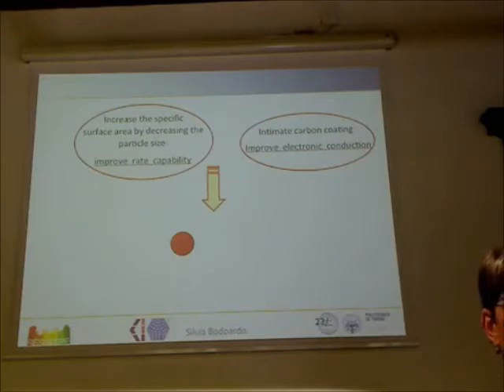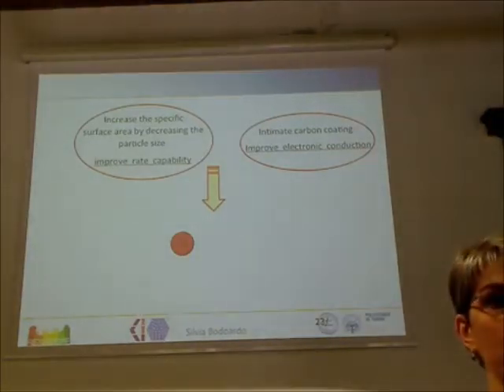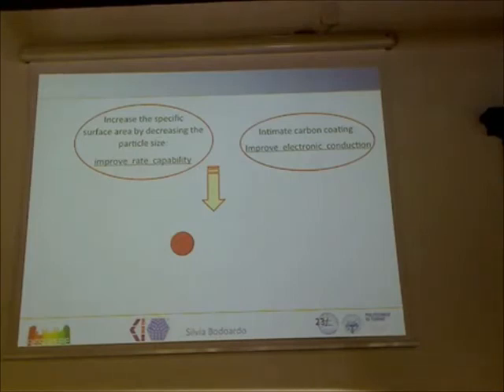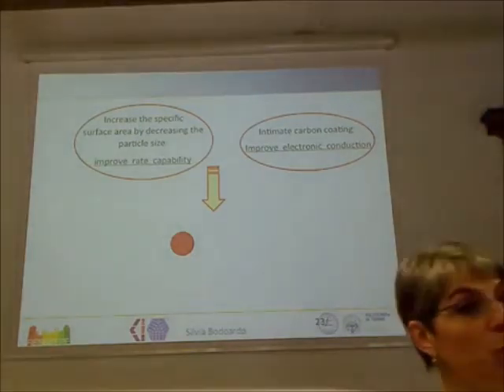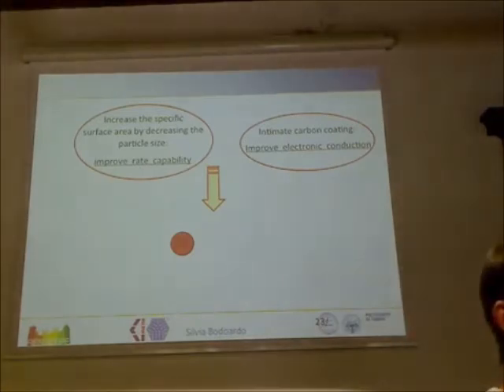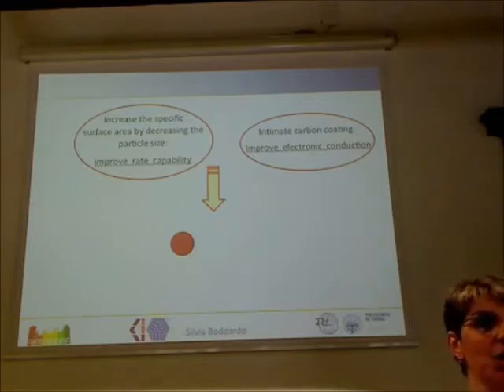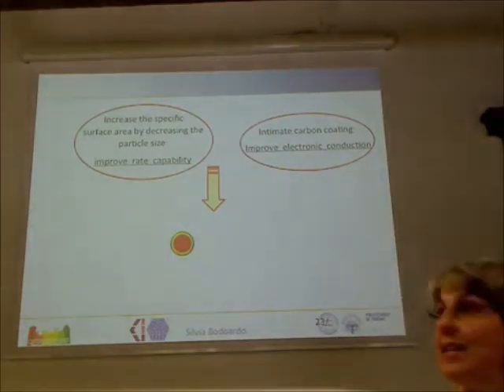Lithium iron phosphate, as I said, is a very nice and good material. Now it is the one mostly used for the application. It has a big drawback, which is that all these materials, oxides, phosphates, or salts, in practice are not electron conductive at all. And this is a big problem, because we need electrons to arrive in the particle, make it be reduced, or go out and be oxidized. But if they are not electron conductive, electrons cannot enter the particle. So in this case, the reaction occurs only on the surface. So most of the active material is not working, and this can be a big problem.